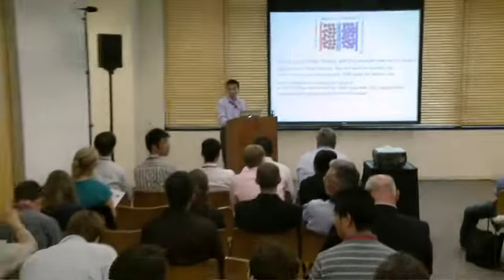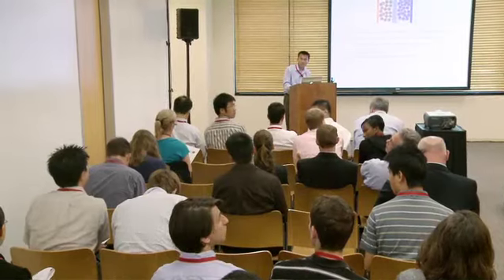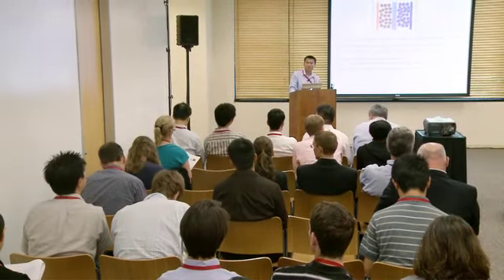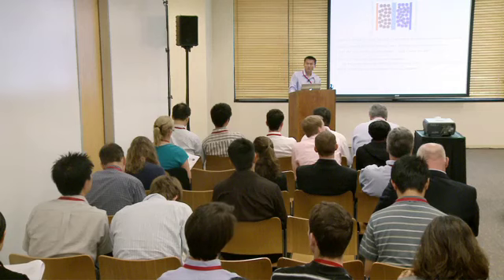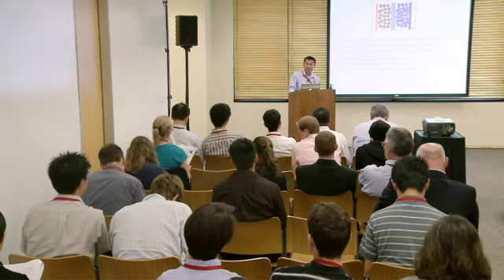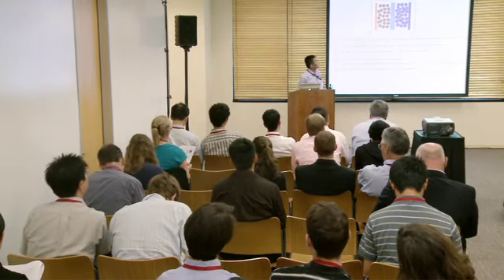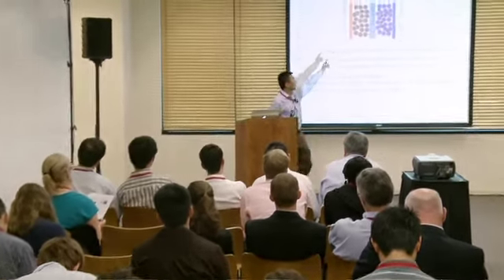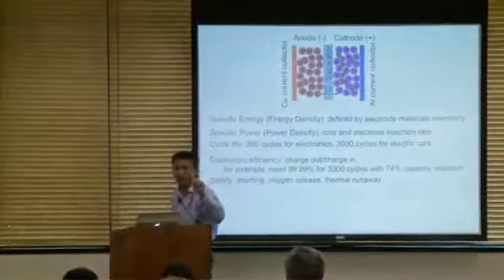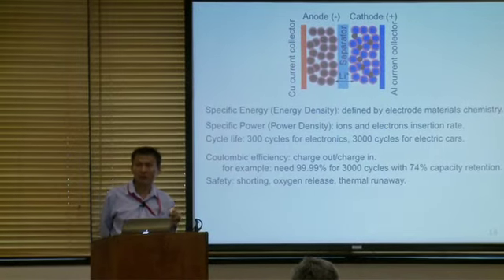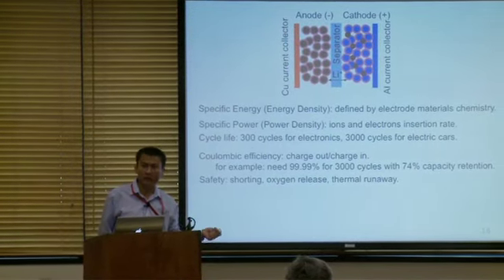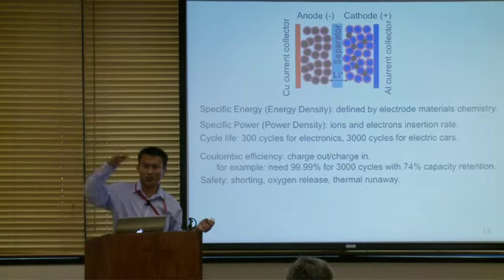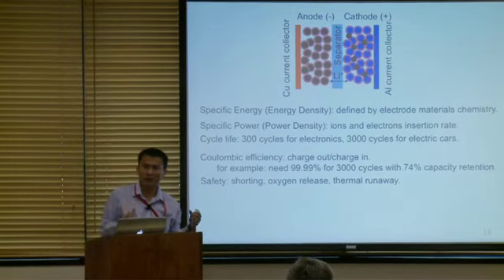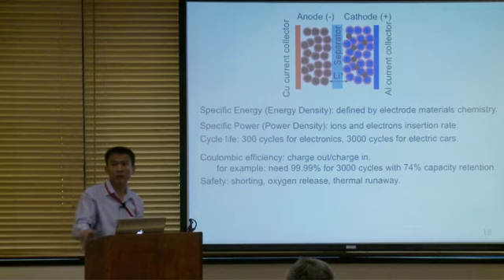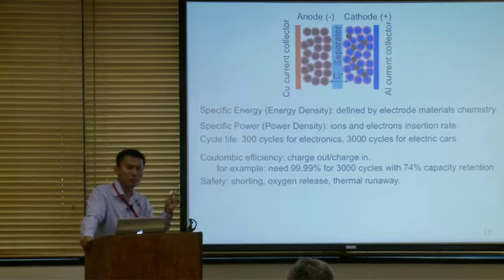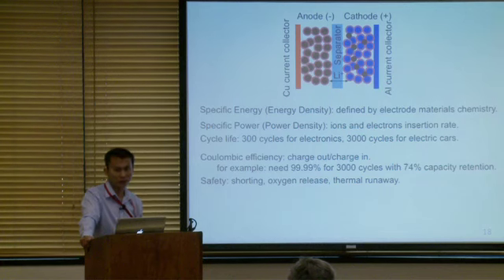Question? You mentioned that you could lose electrons or lithium. Are you losing it through reduction of lithium into metal form? Is that how you're losing it? No, if you lose it, most likely it's because you have organic electrolyte inside the batteries, and they like to react with very reactive negative electrodes. They also like to react if the positive electrode voltage is high, and they get oxidized. From a lithium compound, you lose the lithium, and it forms a lithium compound on the surface of the electrodes.